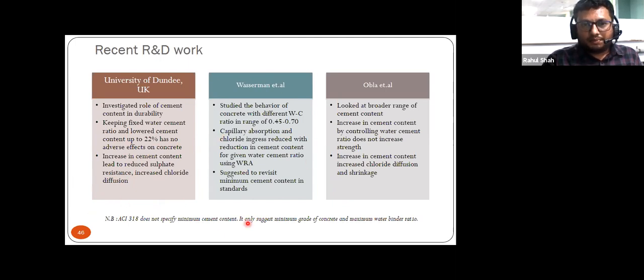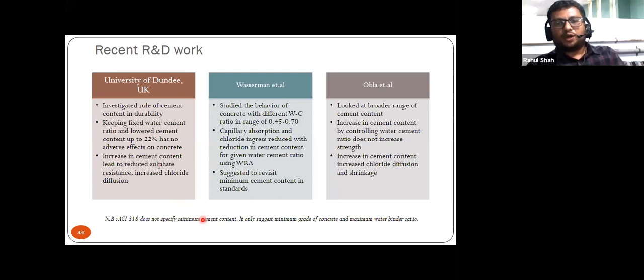The second study was on the behavior of concrete with different water cement ratios in the range of 0.45 to 0.70. They observed that capillary absorption and chloride ingress reduced with reduction in cement content for the water cement ratio, using water reducing admixtures.